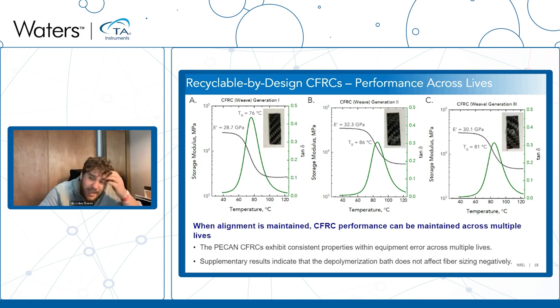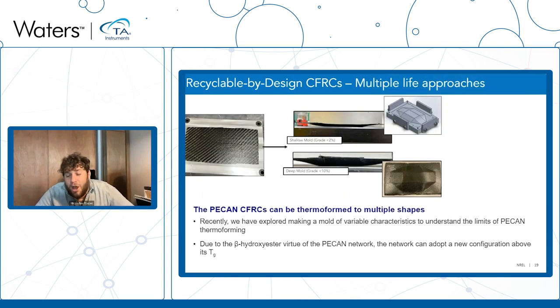We're redoing this data currently for a publication, or at least that's what we talked about yesterday. But we hypothesize here that we're effectively sizing our fibers throughout the depolymerization process, which is why we get better performance in the second and third life relative to the first life. So we've shown through this approach, through redesign using bio-based monomers, that we can reuse these materials over multiple lives themselves.